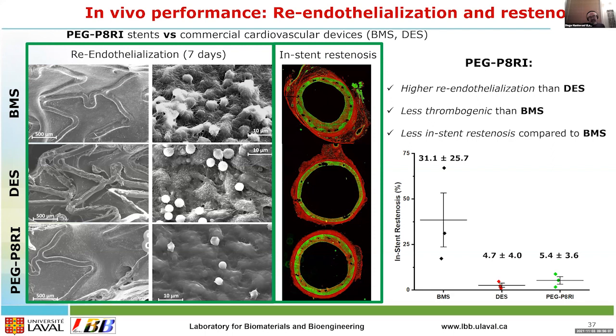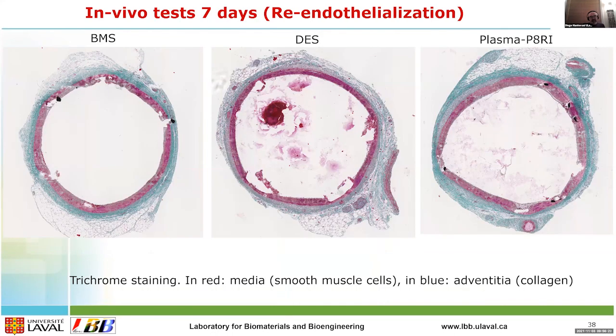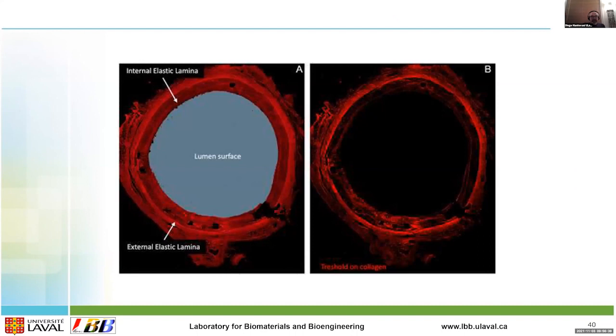And this is the thickness of the capsule, and generally you see a confluent red line. This means endothelialization is confluent. This is also mentioned here: bare metal stent, drug-eluting, and the plasma P8. And this is the lumen. Here is the heart and the coronary, so it is patent. And this is the internal elastic lamina and the external elastic lamina, practically intact. So this means the implantation of a stent, after 28 days, does not bring any major effect or complications in the stent.